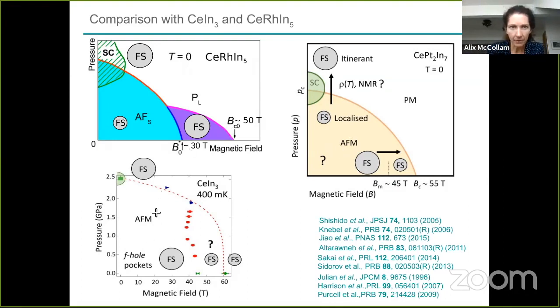Cerium indium 3 is the other member of the family. The Fermi surface is small geometrically, but it does contain the f-electrons. There are small hole pockets of the Fermi surface observed in this region at a very low magnetic field. At high pressure, this also has a small dome of superconductivity, and the Fermi surface is thought to be large, or it has been measured to be large outside here. So there's probably no transition of the Fermi surface in this region.